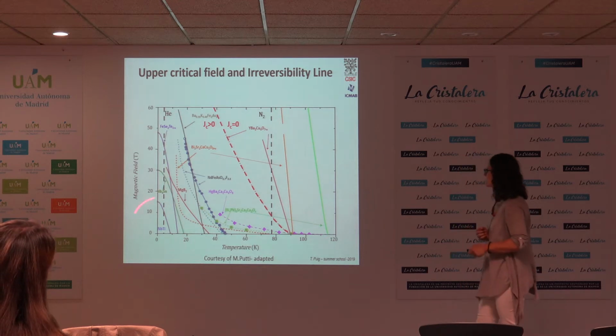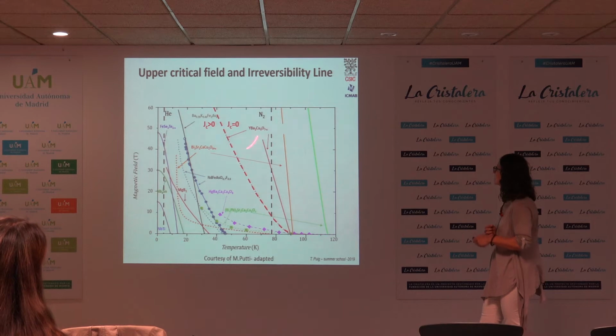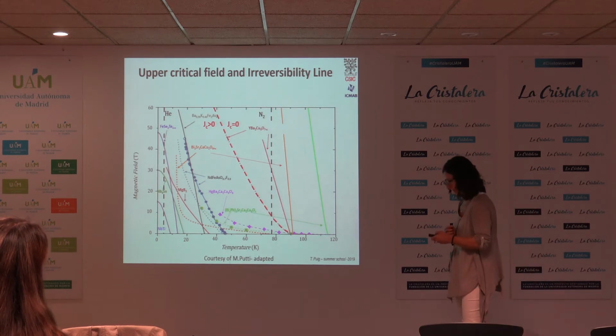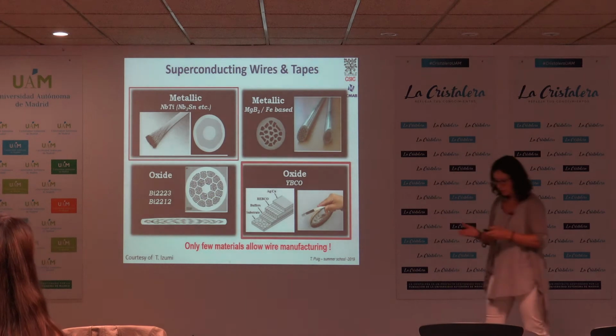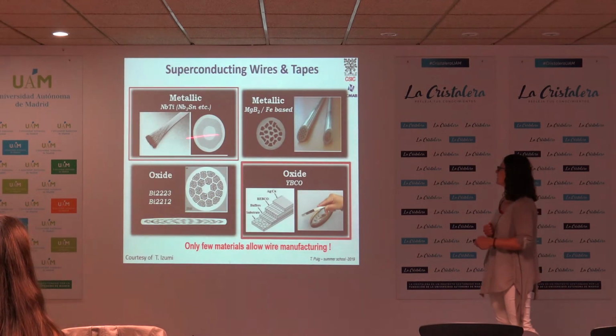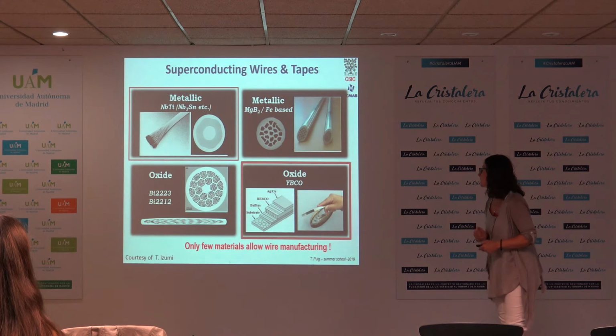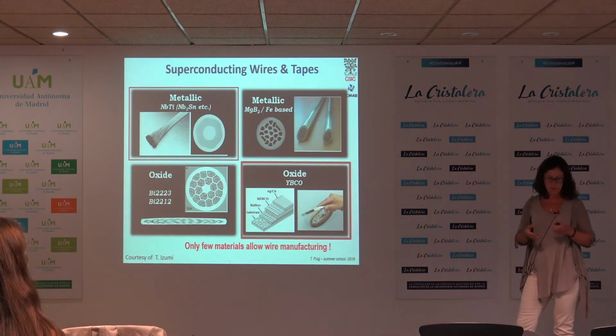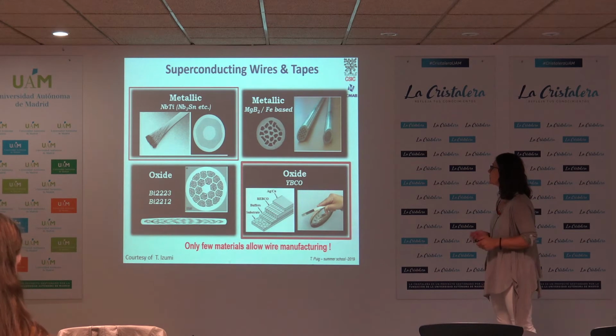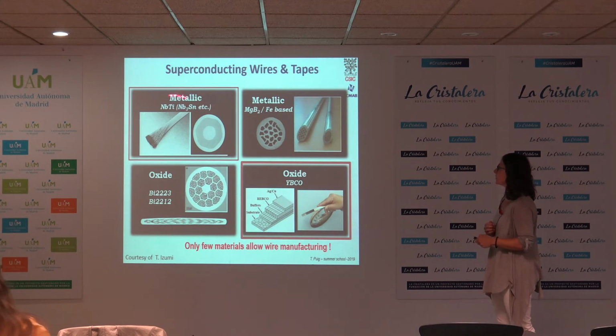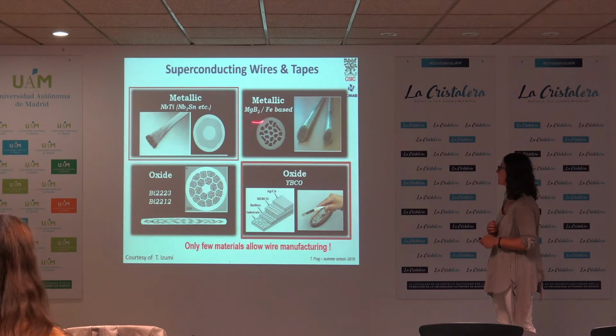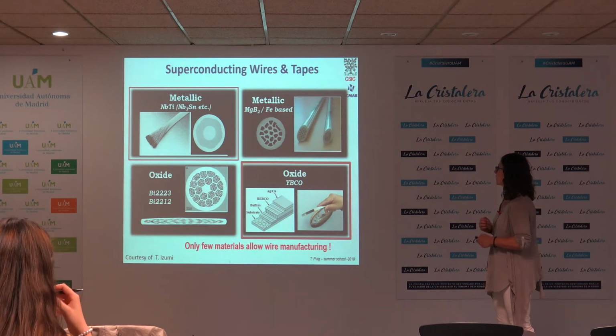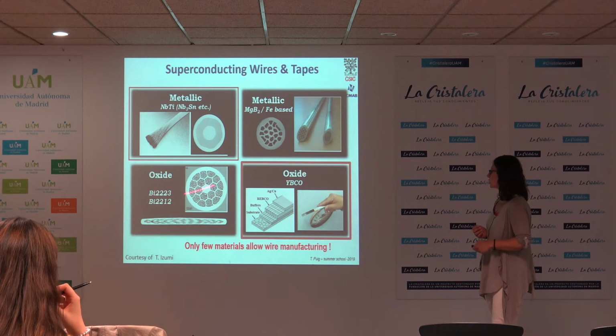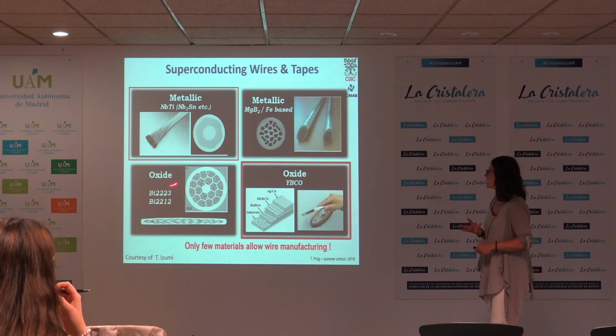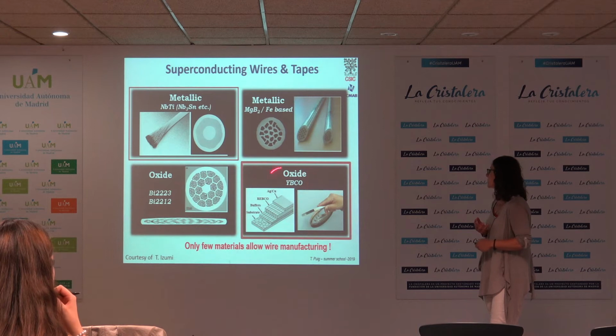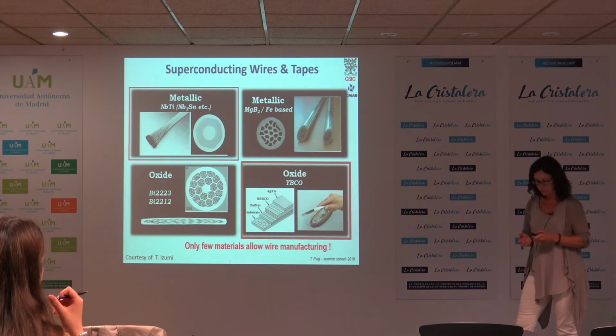And we see here the low TC, the magnesium diboride, the iron-based, and the cuprates. In fact, from all these materials that you have seen up to now, there are only these ones which have allowed making wires and therefore being able to do applications. So we have the niobium-tin and niobium-titanium as low temperature superconductors, and we have the magnesium diboride and the iron-based, which were more recently discovered, and then we have the oxides. The cuprates, so the bismuth phases, and then the YBCO, which at the moment is the one which is able to go to higher magnetic fields.